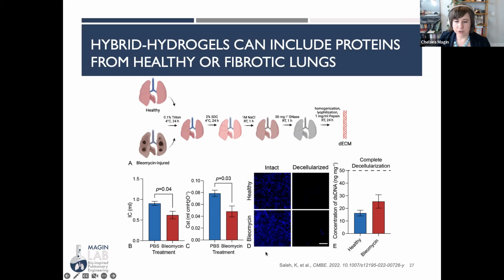In this figure, we show intact lung tissue has many, many cells in it by staining with DAPI for the nuclei. And then when we decellularize the tissue, we see virtually no cells. We also confirm decellularization by looking at the concentration of double-stranded DNA that was left in the tissue. You can see that both healthy and bleomycin after decellularization are below the cutoff of 50 nanograms per milligram.